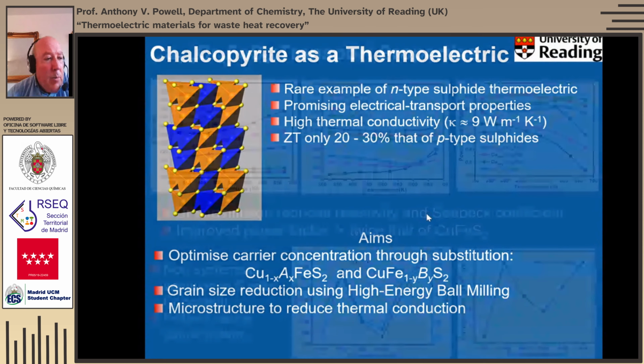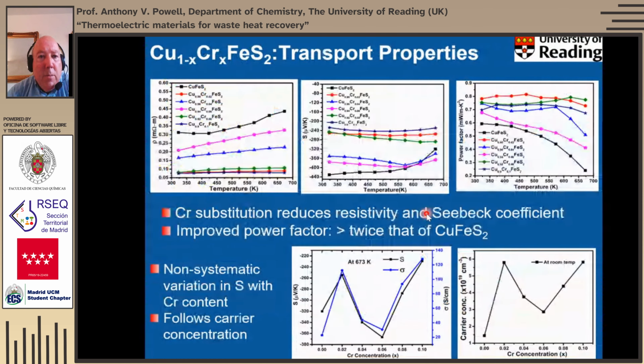So I'll just choose one example from this system, which is the copper chromium system, where we've substituted copper with chromium. And what we find is that if we do that, we improve the resistivity. So the resistivity falls quite dramatically. And also, surprisingly, we don't impede the Seebeck coefficient as much as we might have expected for this reduction in resistivity. So although the Seebeck coefficient does indeed get smaller in absolute terms, it's not as much a reduction as we might have expected. And therefore, we almost double our power factor compared to the end member phase.